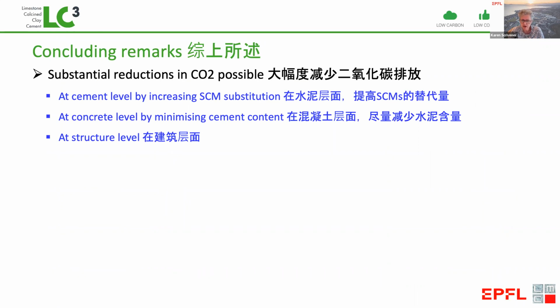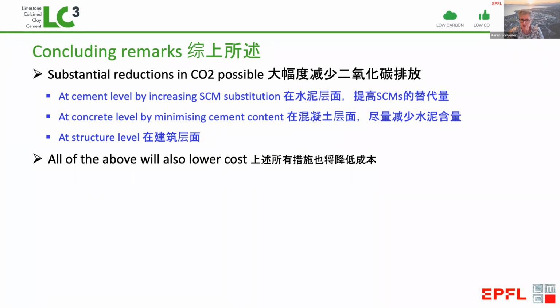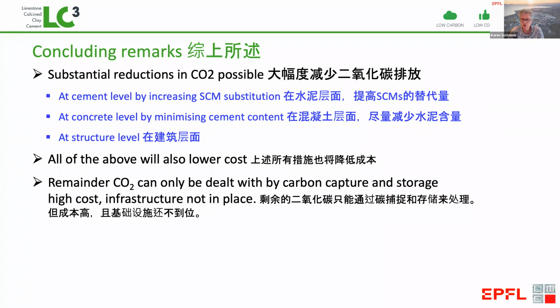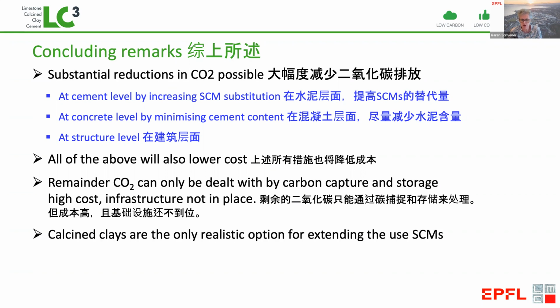We can work at the cement level by increasing SCM substitution. We can work at the concrete level by minimizing cement content, and we can also work at the structural level. All of these will generally lower cost, so very good news. We will never be able to produce completely zero carbon concrete by these means. We'll always have a small residue that has to be dealt with by carbon capture and storage, but this has high costs and the infrastructure is not in place. So it's very important to look at all these other levers before we resort to carbon capture and storage.